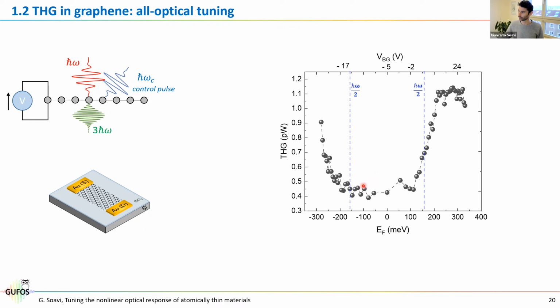And again, you see that for small values of the Fermi energy, the response is small and flat. And then as we hit this special point, h bar omega divided by 2, we have this very rapid increase on both sides of the Dirac cone. So first of all, we do this optoelectronic characterization, and we see that we have this gate tuning of the third harmonic.